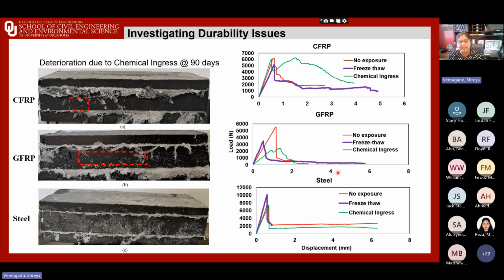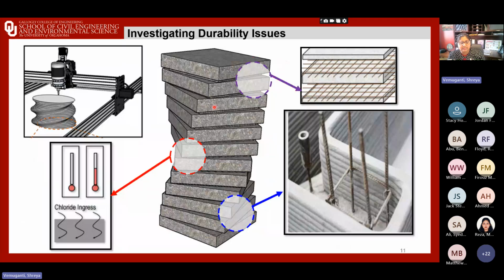Whether it's freeze-thaw or chemical ingress, the message we got from this pilot study was that these weak zones can inherently create deterioration mechanisms or accelerate them. It's important for us to understand how this affects us in the long term. So these were conducted up to 90 days, which is about 3 months, and we tested these specimens. Taking this knowledge, up to this point where we've studied these manually created interfaces under freeze-thaw and chemical ingress, the key lesson is that interfaces can control durability.